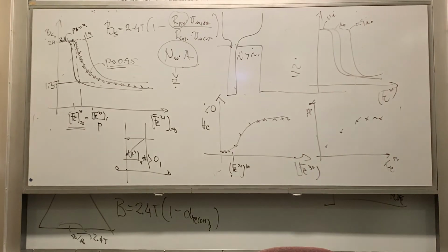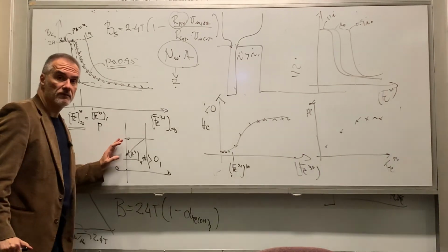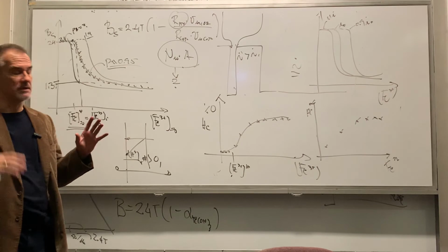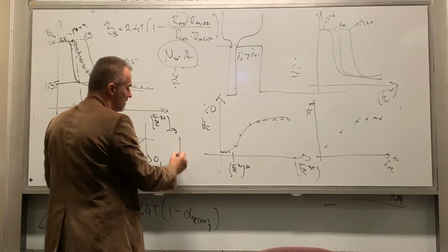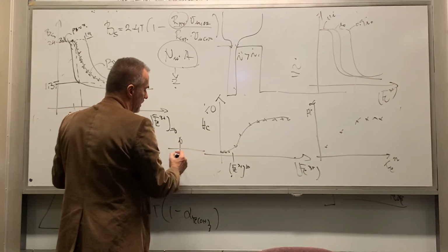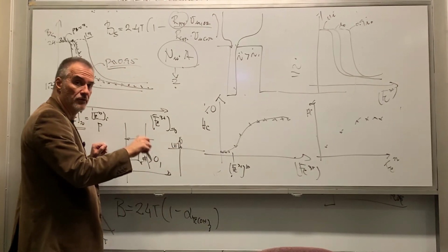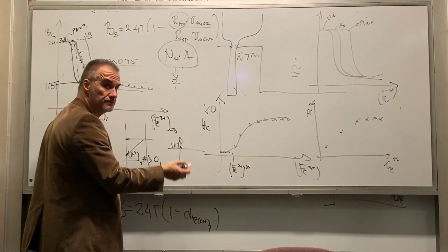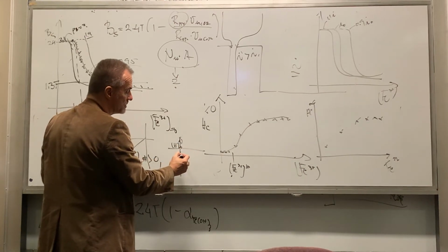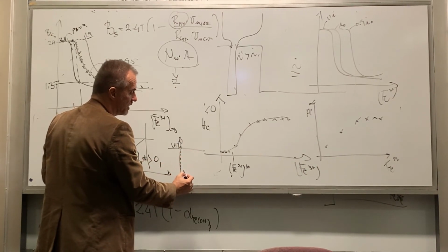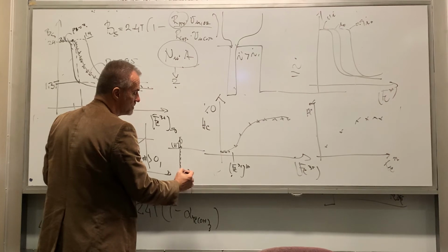However, when we do pulse deposition, there's an unsteady state, which means before we turn on the potential, it's H plus in the bulk. And then for the given current, as we are waiting, the concentration drops down and becomes some H interfacial, which is lower, right?